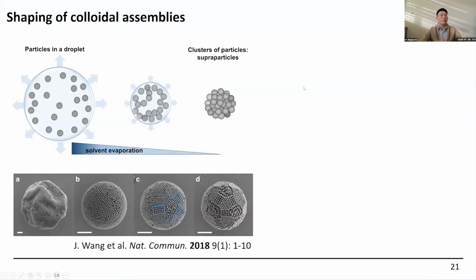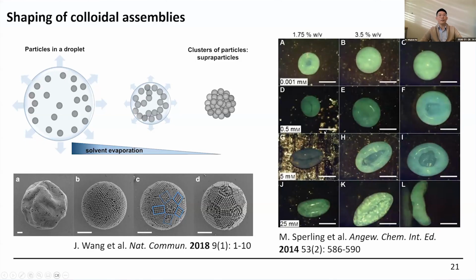And this is work from another group, from the group of Professor Vogel in Erlangen, and they show that they can control the evaporation speed during the assembly process. Then in the end, they can control the nanoparticle assembly structure from a very random packing to a crystallized packing. Furthermore, with this technique, we can also break the symmetries into different shapes. From Professor Orlin Velev's group in the US, they add sodium chloride, the salt, inside the droplets, because the sodium chloride will cause the nanoparticles inside to prematurely aggregate.